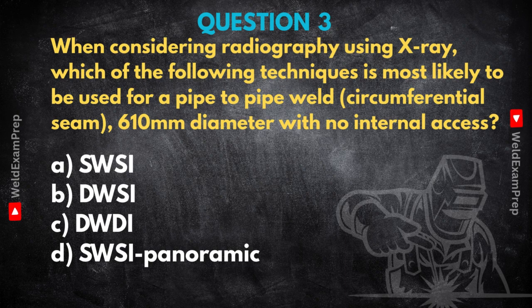Given a large diameter pipe like 610 millimeters and no internal access, the technique you'd most likely use is B, DWSI, double wall, single image. Okay, why that one specifically? Well, think about it. With DWSI, you put the X-ray source on the outside of the pipe, and the film goes on the opposite side, also on the outside. The radiation goes through both pipe walls, top and bottom, but, and this is the clever bit, only the image of the weld nearest the film gets recorded clearly enough to interpret properly. For a full circumference on a big pipe, you'd just move the source and film around, taking multiple shots to cover the whole weld. It neatly gets around that no internal access problem.